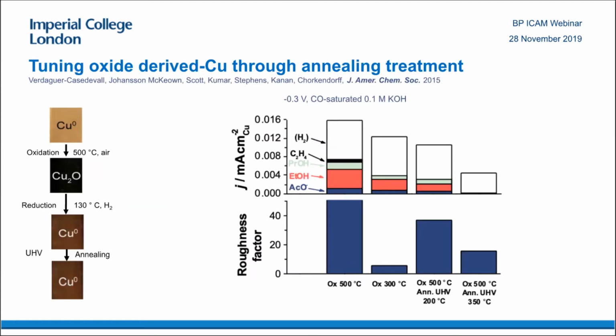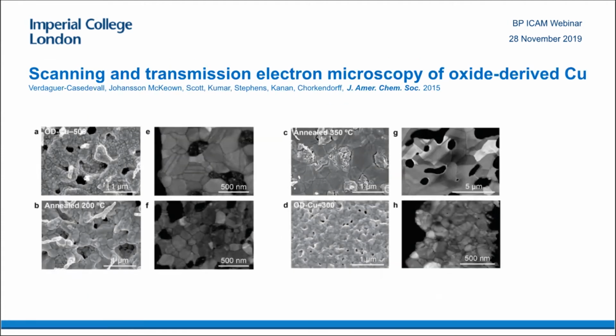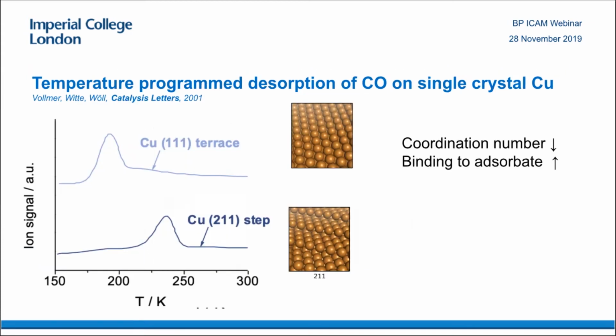So we sent a PhD student out to Stanford, to Matt Kanan's group, to probe this, Arnau Verdaguer Casadevall. What he found is that by changing the annealing treatment, you can change the product distribution quite considerably. You could also change the roughness factor. The roughness factor didn't always correlate very strongly to the annealing treatment. If you look at the electron microscopy of these catalysts, you could see they're very rough surfaces. It's a bit difficult to figure out what is the actual active site on these surfaces that is responsible for the enhanced ethanol production.